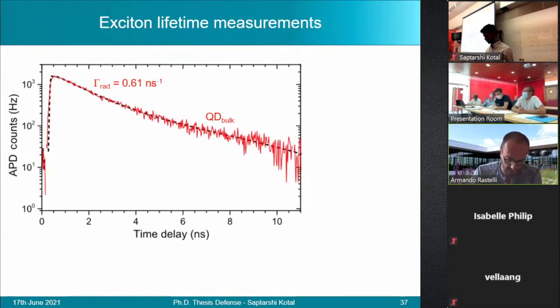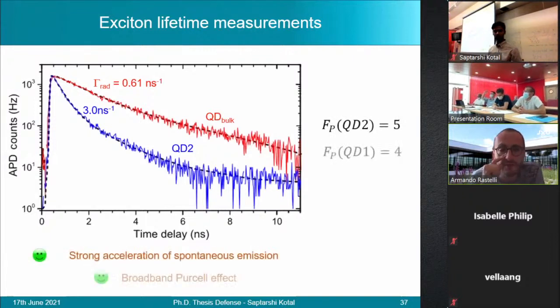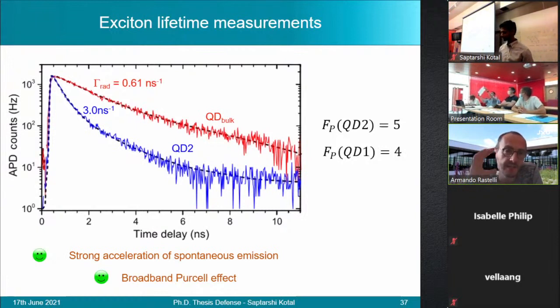So what you use is a non-resonant excitation. And of course, if we look at these decays, you could have different things to be considered. First of all, you excite non-resonantly, so you need also the carriers to relax into the quantum dot, to reach the ground state before recombining. And essentially, you are implicitly assuming that this relaxation time is negligible. Can you comment on that? Who tells you that this 0.61 is really the radiative decay and maybe half doesn't come from the relaxation time?